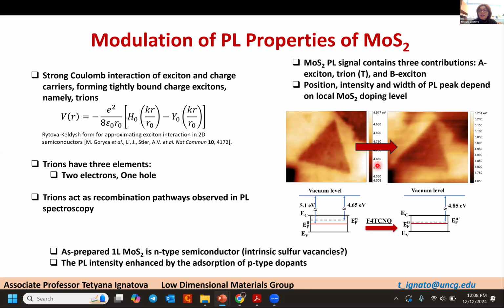To probe how much we dope the material, we applied Kelvin probe KPFM techniques, and just by calibrating these results with some reference material, we can calculate how much we move the doping level and what is happening upon applying this p-dopant on top of the pristine as-grown molybdenum disulfide flake.